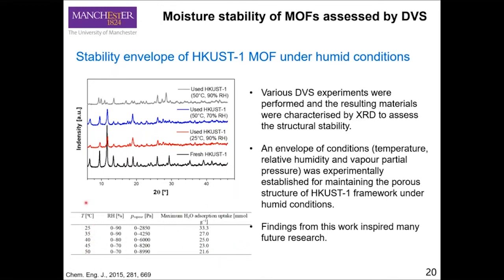And the temperature here was limited by our old DVS system. I think the maximum they can only go to is 50. So with this kind of window, we do provide some information. If you want to use the materials in practice, then you have to make sure you design a process to host the materials, because this material has some very interesting properties.